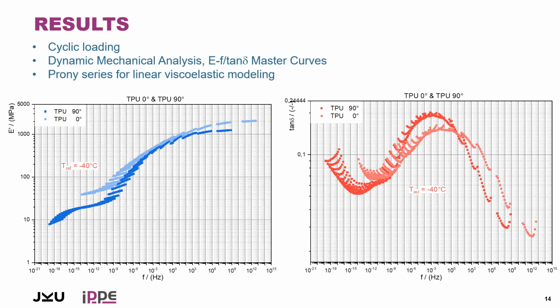And then you see here the master curves for the thermoplastic polyurethane material and also for both orientations. Does it mean we have a kind of anisotropic master curves or anisotropic viscoelasticity models based on this test? On the left side, you see the storage modulus values, but we also determined loss modulus and then calculated tangent delta, and not only constructed a master curve for the modulus, but also constructed a master curve for the damping behavior.